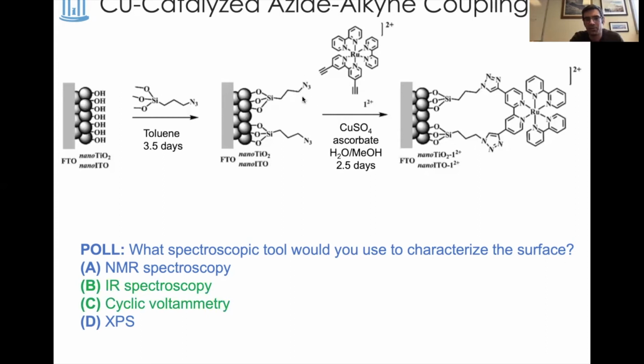In part because we have these azide linkages, and then there's also alkynes. So those are two nice, strongly absorbing IR handles, and the triazole even has some signatures as well. But what ended up being really helpful was to look at the IR spectra of the surface before and after this silanization, and you could see the azide stretch appear. And then after addition of the ruthenium complex, you could watch the azide stretch disappear. And you could also look for alkyne to know if there was any unreacted ruthenium complex left that didn't undergo the click reaction and was just sort of physisorbed to the material.